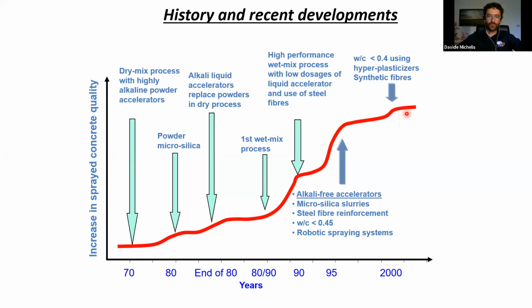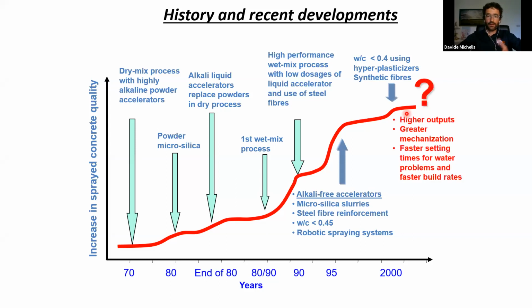Nowadays, we are looking to, and we are succeeding in getting, mix designs with water cement ratios below 0.4, and also the use of synthetic fibers, structural synthetic fiber, is spreading around. So we are having very good results also with the use of polypropylenic fibers. What's in the future? Hopefully, also looking for a higher production rate.